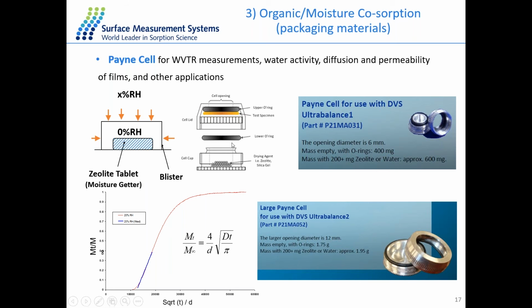the top. We can put some drying agent inside the cup here, and the drying agent will keep 0% humidity throughout the experiment. And then we can change the outside concentration with our DVS instrument. So the vapor molecules will just go through the film sample from the top to the bottom in one direction only. Then we can calculate the one-way diffusion coefficient or the permeability for the film sample.